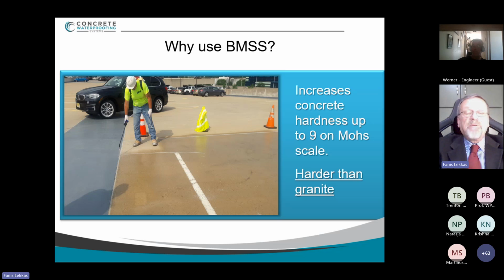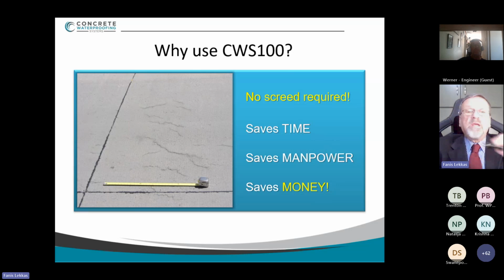Finally, and very importantly, this technology, when applied on concrete and properly watered in for 3 days, then 7 to 10 days later, the formation of this gel has concluded. And as a result, the surface has increased its concrete hardness up to grade 9 of the Mohs scale. Think about it. Granite has a hardness between 6 and 7, 5.8 to 7, depending on the geography that we mined it out of. So that means that now we have increased the hardness to a much higher level than granite, and this in plain English means that we do not need to use a protective screed to protect the waterproofing.